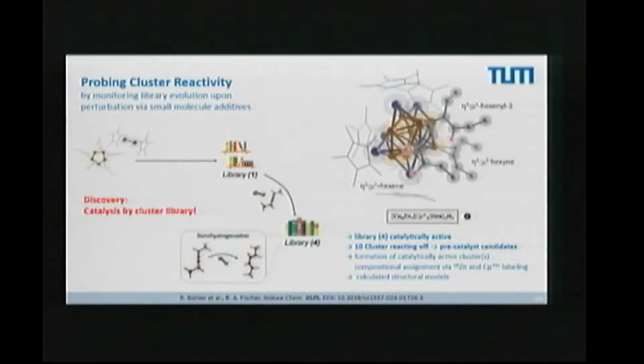Now, last example. Again, we create the library, and then we put in simultaneously an alkyne with a triple bond. It's hexyne, where the triple bond is symmetrically in the middle. It's 3-hexyne. And we have hydrogen present. And what we see is that we have now a catalytic conversion of the hexyne to the hexene. It's a semi-hydrogenation. It will not hydrogenate to the hexane. It stops at the semi-hydrogenation, which is an important process also in the industrial purification of hydrocarbons.